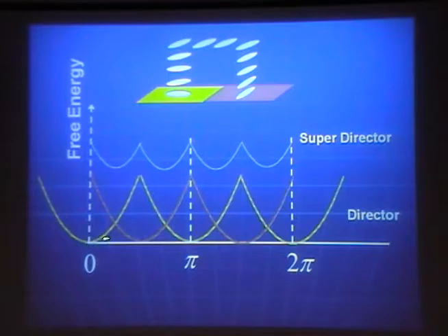You can never achieve the lowest free energy because of the orientational conflict existing or induced on the surface. So the real spirit of this patterning idea is to raise the ground state energy beyond just a uniform orientation, so that you can manipulate the landscape of the free energy to create a metastable point in many different orientation states. So the switching can take place from this 45 degrees to 135 and so forth.